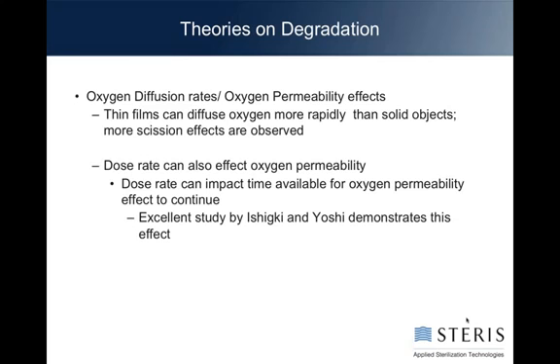One of the biggest theories on degradation is by looking at the oxygen diffusion rate into the product. And this actually accounts for one very well-known phenomenon, that thin films versus big, bulky products actually experience more rapid decline. And that's because the oxygen can permeate through them readily and much more quickly, so the change can occur.